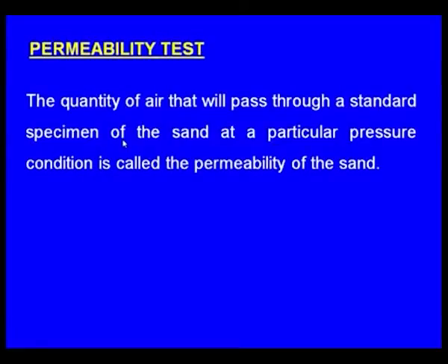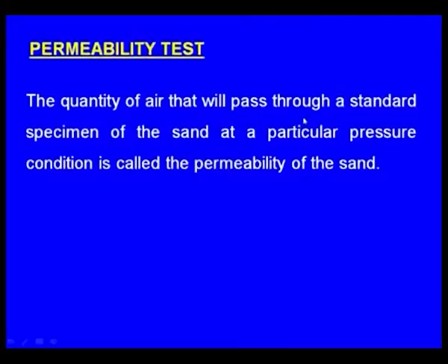If the permeability is not adequate, what happens? The gases thus produced will be accommodated inside the mold and finally lead to gas and blowhole defects. Now, how do we know whether our sand has the required permeability or not? We have to determine it. The quantity of air that will pass through a standard specimen of the sand at a particular pressure condition is called the permeability of the sand.